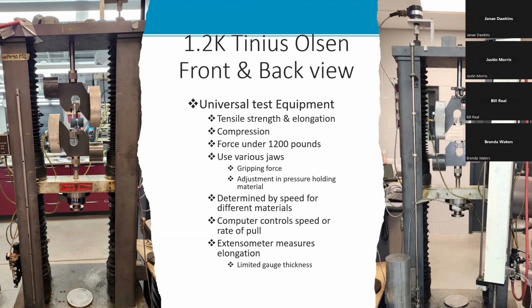You also have an extensometer, which measures the elongation, but the thing with your extensometer is it's limited in the gauge thickness. So that's one of the reasons why your molds are very important and the material has to be cured properly, because if your material is too thick, it's going to be too thick for your extensometer.